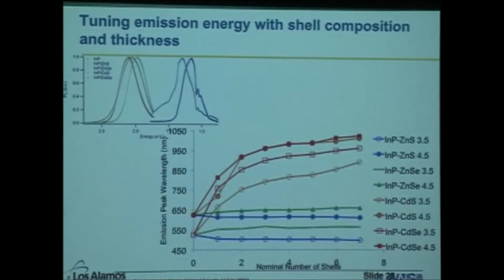And just to give you an idea, with the cadmium selenide containing shells, we're able to tune emission energy with its thickness. As we increase the number of cadmium sulfide or cadmium selenide shells, and these are all the red guys here, you can see our starting emission is in the visible, but very, very quickly as we increase the number of monolayers, we're pushing out into the near infrared.